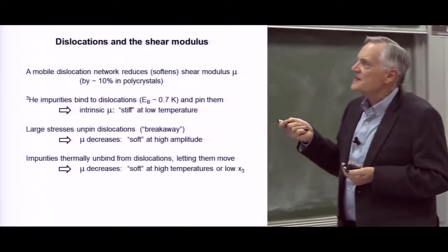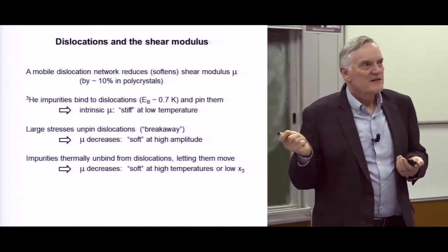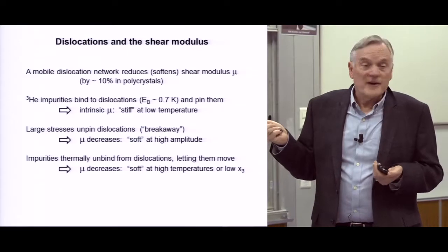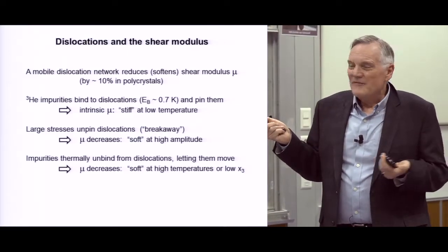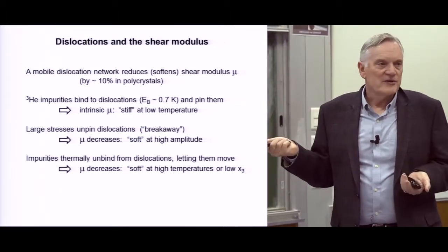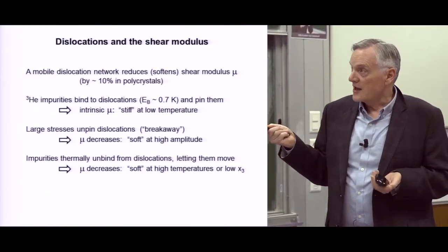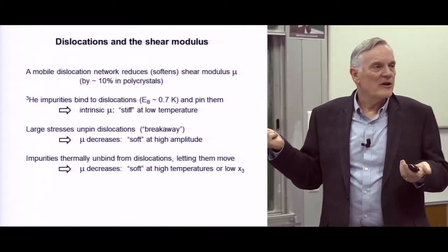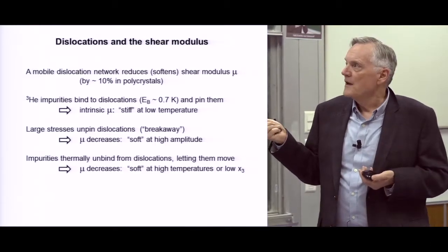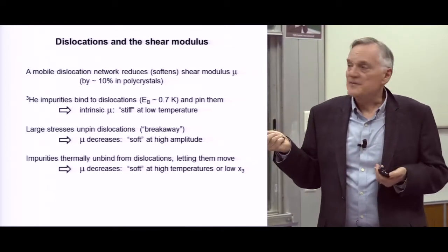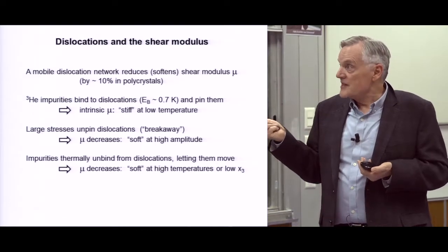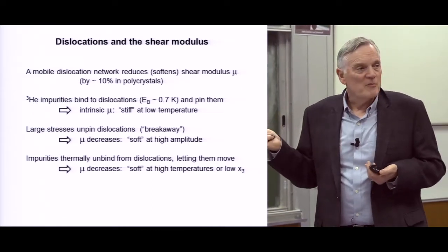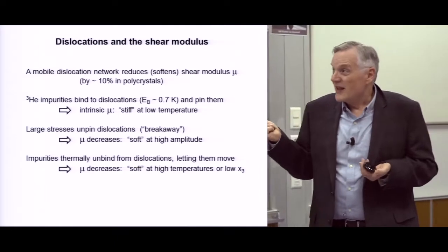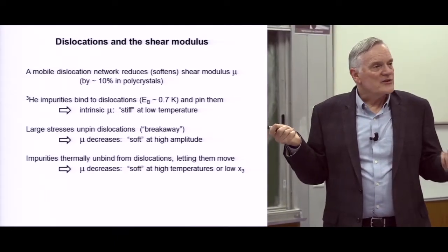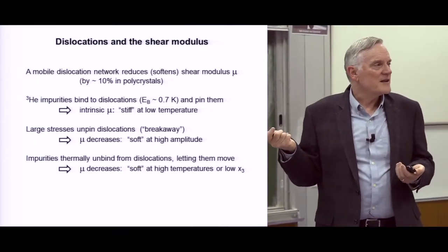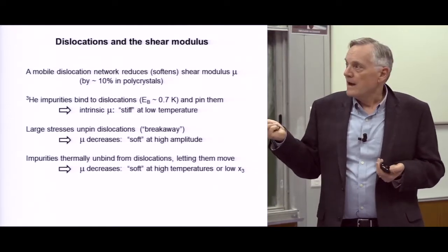Okay, so this is the summary of how dislocations are expected to affect and do affect the shear modulus. If you've got a mobile dislocation network, you're going to soften your crystal's shear modulus. And what we saw in our crystals, which are, by the way, polycrystals, just kind of the way we grew them, was about a 10% one, and that's within the range you expect. Helium-3 impurities, even small numbers, bind with a binding energy of about 0.7 Kelvin. We measured it. And then they pin them. And that means that when they go to low temperature, it's completely pinned. You go right back to the same elastic modulus you'd measure in a perfect crystal.